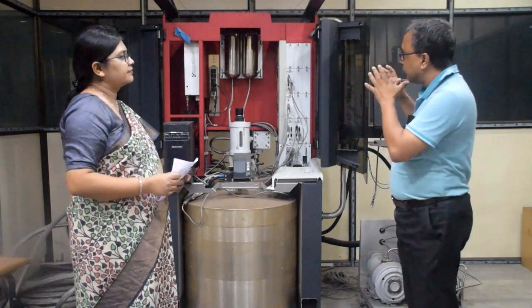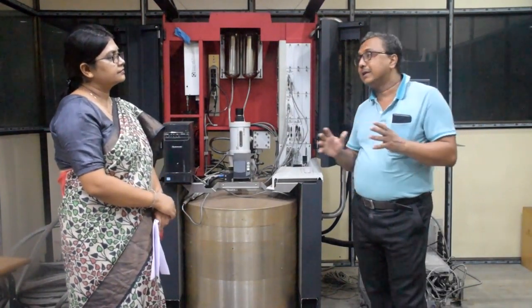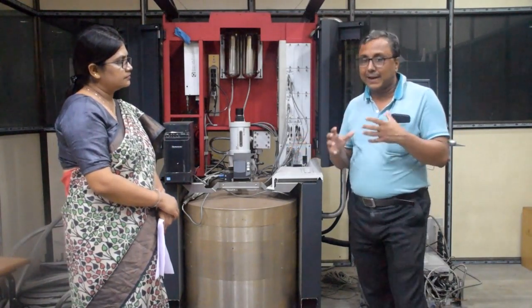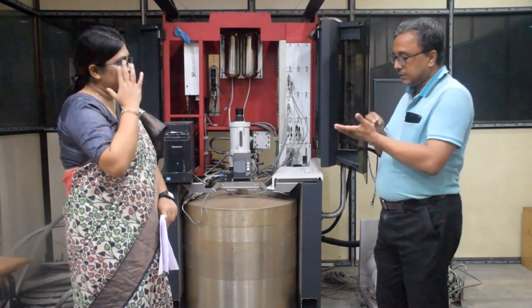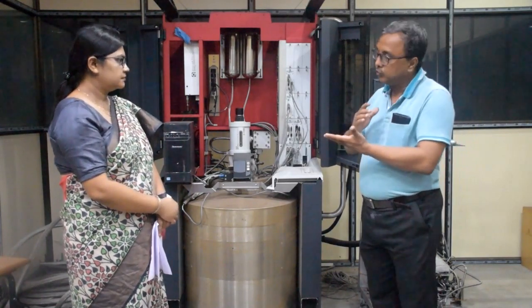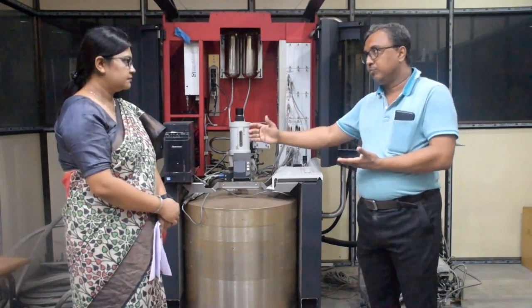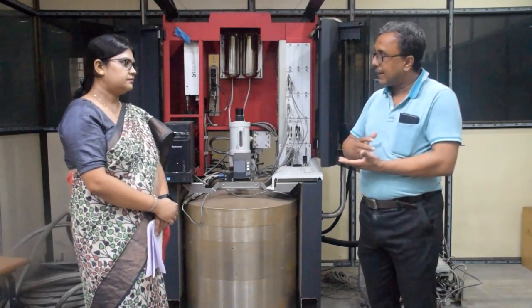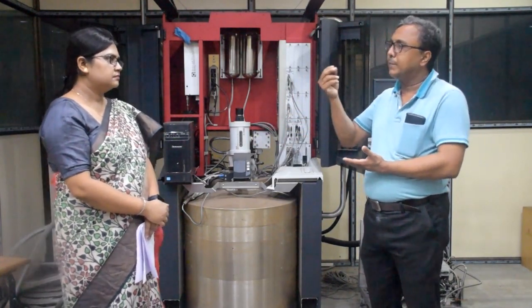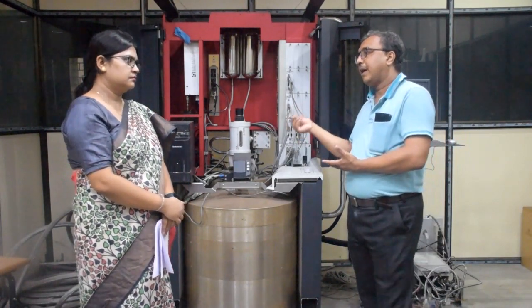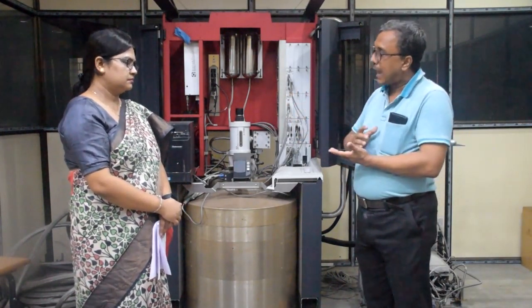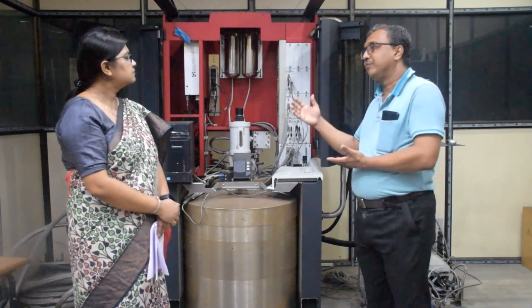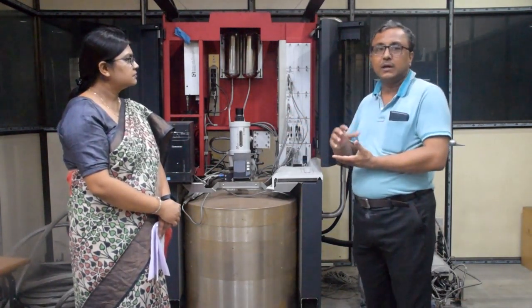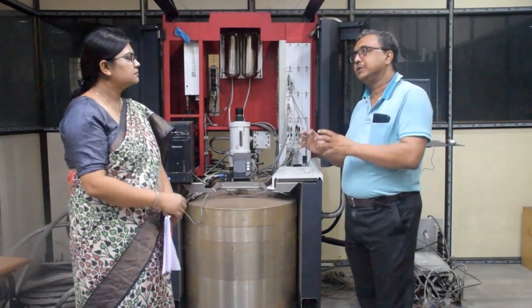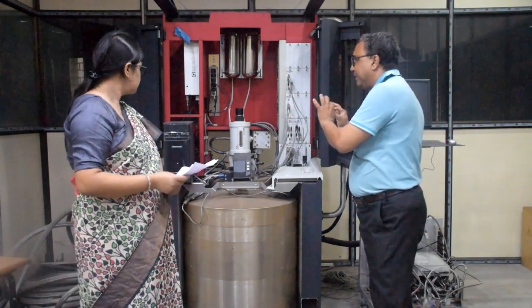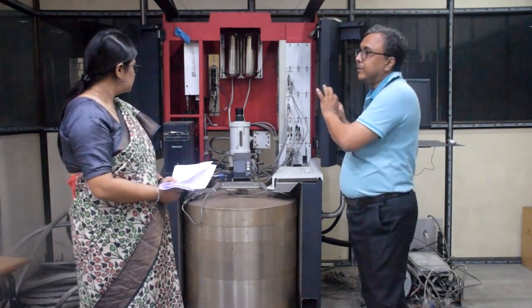So as I told, this is one of the most sophisticated instruments for measuring the magnetic structure, magnetic phase, and magnetization of a material. It can scan from 2 Kelvin to room temperature, 300 Kelvin, and can detect any change in even a very small amount of magnetic moment. It is a very sensitive instrument, and over temperature change and field variation up to 12 Tesla, you can check the change in the magnetic property of the system. Even a very feeble magnetic moment you can identify.